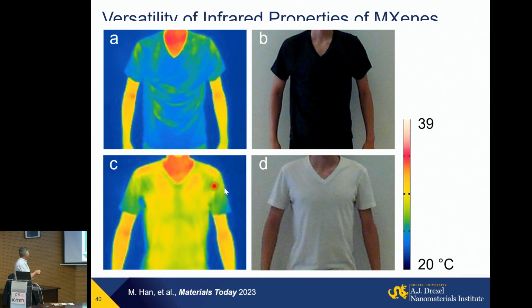And this is an example, one of my students, Teng Zhang, wearing a t-shirt. This was a white t-shirt. This is his thermal imaging picture in a cotton t-shirt. After that, we simply washed it in MXene colloidal solution. It becomes dark, scattering black, but you see now it does not emit heat, so it can keep him warm. And imagine with a sub-micrometer film, you can put it on any clothes, and this is definitely not the optimum way to put it. And you can wear a silk blouse, go to the North Pole, and stay warm.